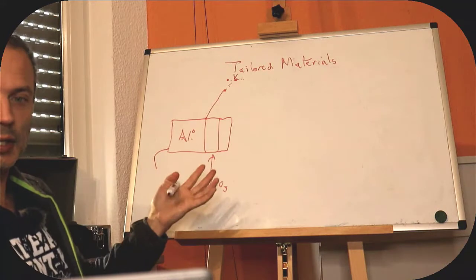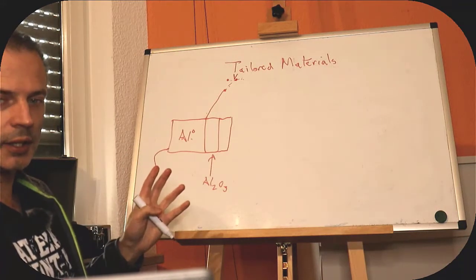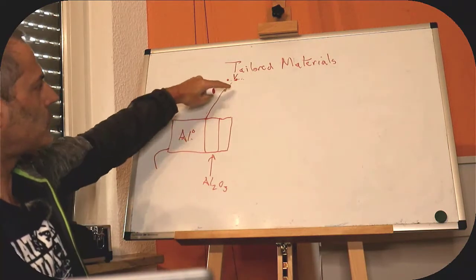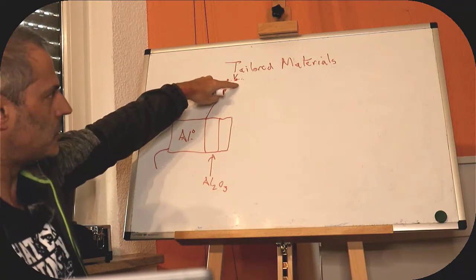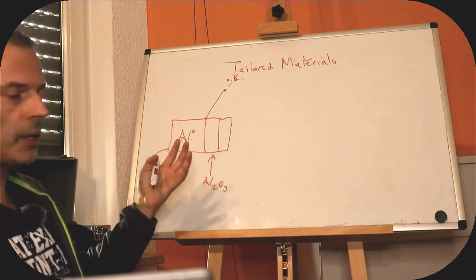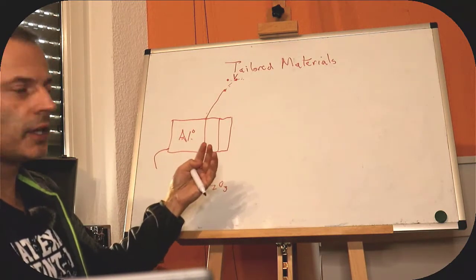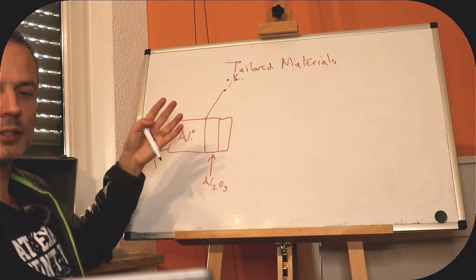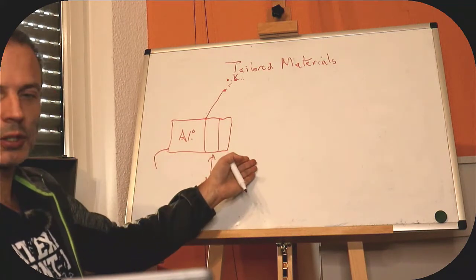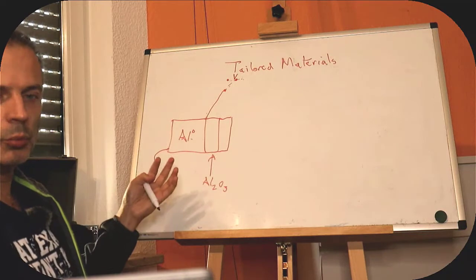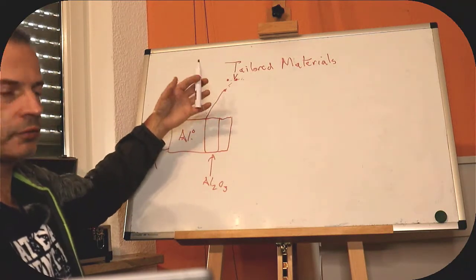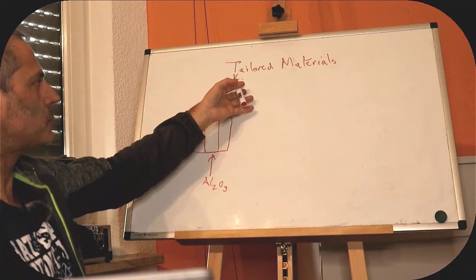So to keep the same angle, we have to go up to here, which means that we will grow some more aluminum oxide. The aluminum oxide will typically get thicker if we put it into a more oxidizing atmosphere. Once we've got it to this thickness, the rate of oxidation doesn't go to zero, but it goes down very, very much because the driving force is this voltage. And the voltage near the surface is the voltage that the outside atmosphere wants it to have. And the voltage in the middle is the voltage that the aluminum wants it to have. So if we deliberately do this, we can generate a coating that is thicker than you would expect.